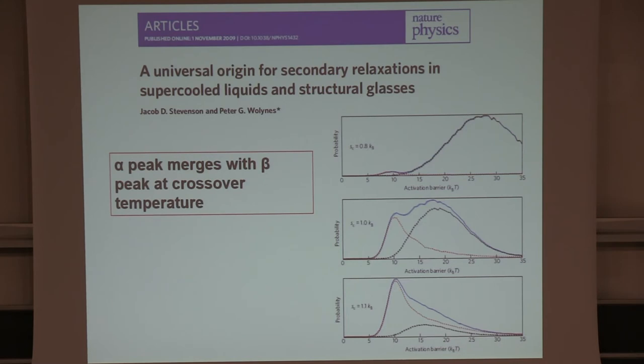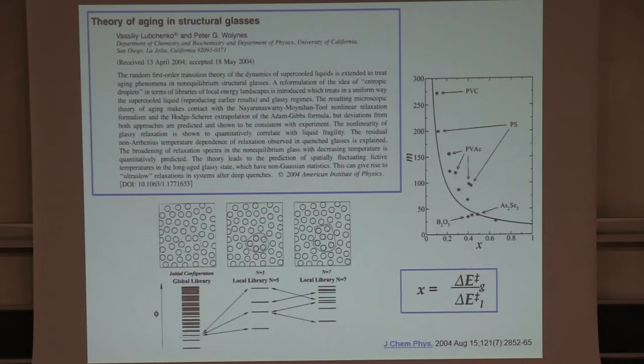In fact, the very stringy things that occur are secondary relaxations. And one sees then if you have a stringy object, it fluctuates more relative to its surface energy. And that's why, in fact, there is a trail of very high energy states that have, therefore, low activation barriers that give rise to the so-called secondary relaxations. Both of these were work done with Jake Stevenson. The other work also involved Jörg Schmalian. Now, everything was about liquids, but I said I'd talk about the theory of glasses.